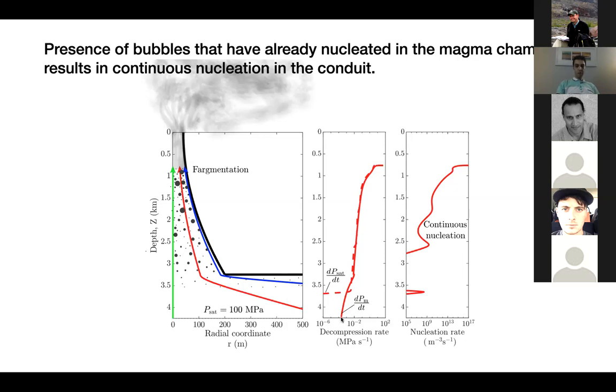First, there are no bubbles. As magma starts rising, water becomes supersaturated. Nucleation is assumed to be heterogeneous again. Bubbles start nucleating in the magma reservoir. As bubbles start nucleating, nucleation rate increases very sharply. At some point, it catches up with the decompression rate and overpasses it. That's where supersaturation pressure decreases, and nucleation rate peaks and drops.